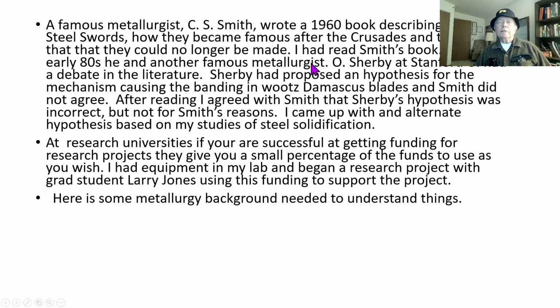He and another famous metallurgist, Oleg Sherby, at Stanford University, had a debate in the literature. Sherby had proposed an hypothesis for the mechanism causing the banding to form in these Wootz Damascus blades. Smith did not agree with it. After I read their paper, I agreed with Smith that Sherby's hypothesis was probably incorrect. But I did not agree with Smith's reasons. The reason was I had been doing a lot of work on steel solidification. As a result of that, I came up with an alternate hypothesis.